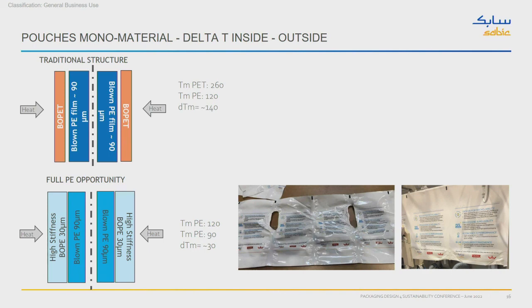We had to do some work. And then what you usually do is change the melting temperature on the inside. We can reduce the melting temperature by using different polymers. Sounds very nice, but your coefficient of friction changes, so your machinability changes. Also the whole packaging, the handling of the reels. Film comes on a reel. At the moment it's, I don't know, 20 plus something, but I think by the end of the week we get 30 and more degrees.